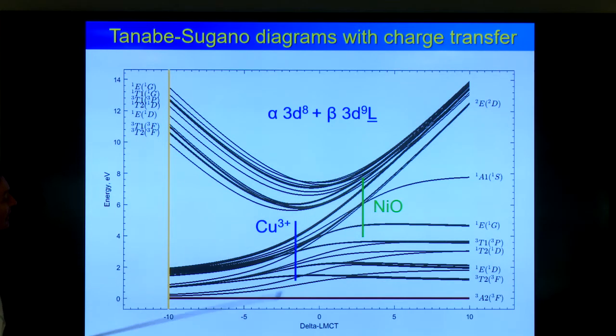If you go from nickel 2+ to copper 3+, you go to negative delta. So this is the copper 3+ in high-Tc superconductors. So delta is -1, and then your ground state is now really a mixture between d8 and d9. You can tell, it's almost a 50-50 mixture of the states. So with this two configuration model, you can describe transition metal systems accurately, and then describe all the possible experiments you would like to do with them.